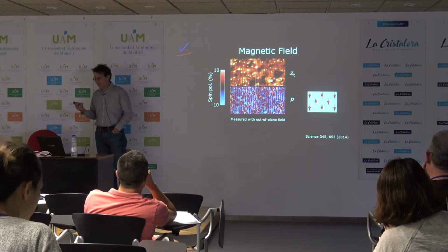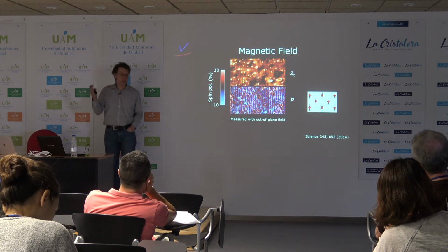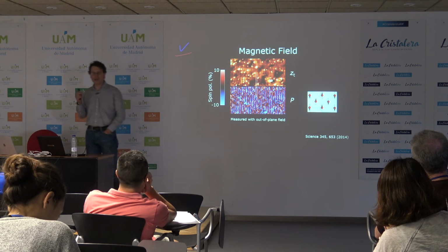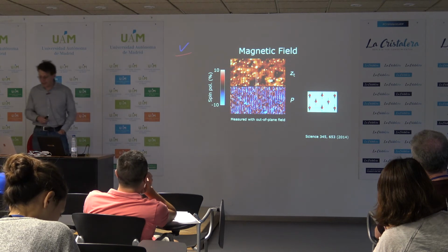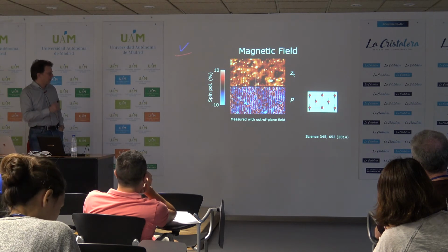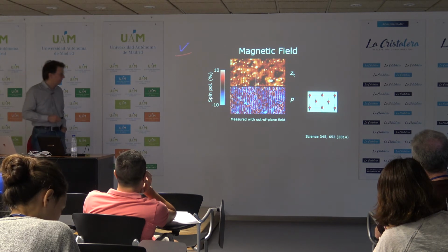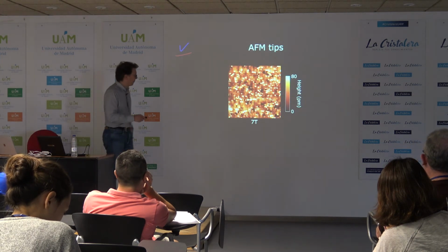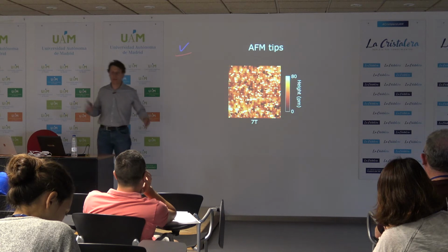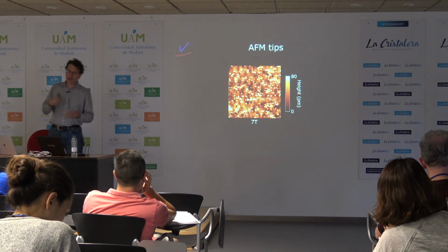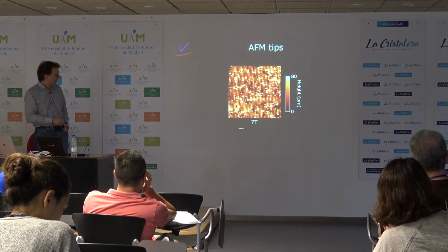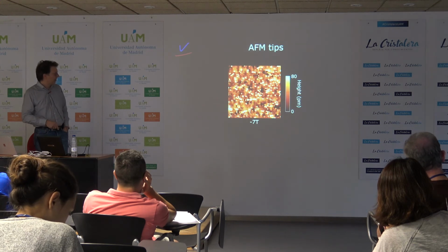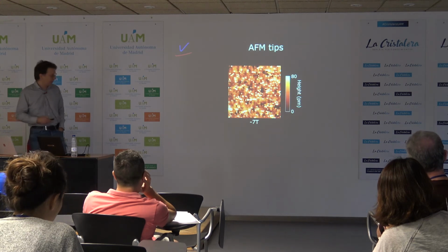So to study, if you like, the direction dependence of our magnetic contrast, we first need to establish what the magnetic nature of our tip is. And we can actually control that by how we prepare it. So one possibility is we can make antiferromagnetic tips if we really pick up a large cluster of the material. And then if we change the magnetic field, there's no change because the tip doesn't follow.